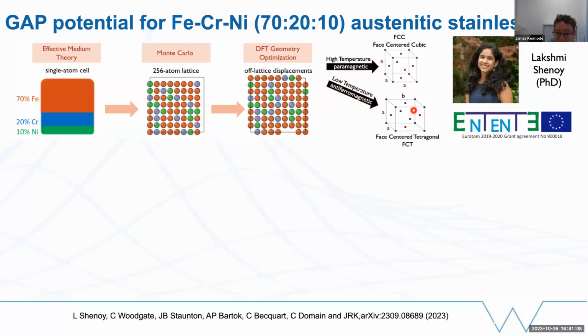We're interested in this low temperature antiferromagnetic part of the response, where actually we get interesting distortion of the lattice. So we don't get a cubic lattice like you would at high temperatures and like you do in simpler materials. We have two lattice components equal and one longer direction associated with ordering of the spin in antiferromagnetic layers, up, down, up, down, up, down, along that long direction. And we struggled to describe this with a GAP model initially when we were using a standard GAP model with 3 species representing the 3 chemical species.